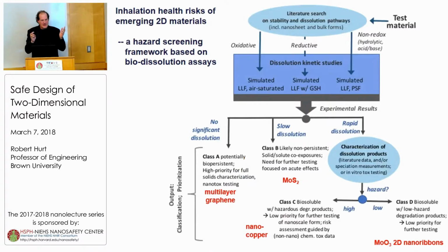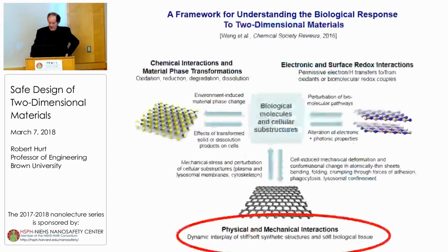Under these conditions, it doesn't mean they're not long-term degradable, but these would be the highest priority materials for more detailed characterization. And one of those would be multi-layer graphene. It's thermodynamically oxidizable, but it's difficult. Kinetics are very slow. And this kind of leads to the last part of my talk, where we now have a material whose solid phase we're pretty convinced is the key to understanding biological behavior, and we need to look very carefully at the nature and geometry of that solid phase.